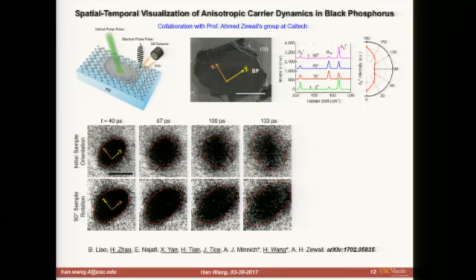These are just images we selected at a particular time, but between these two images we can take like 100 more images in between. So we've been able to make a whole movie of this whole process in both the spatial and temporal domain. This technique is very useful because from this imaging data, you can get a lot of useful information about the hot carrier diffusion process in all directions of the crystal.